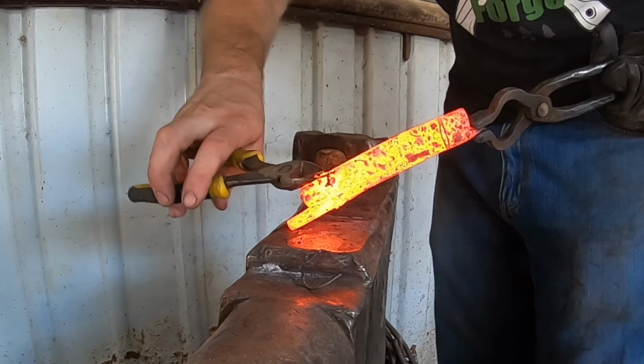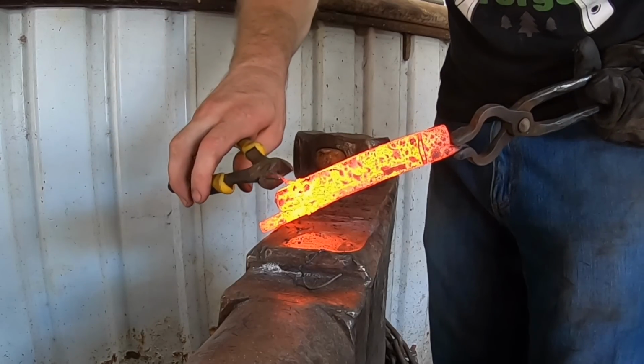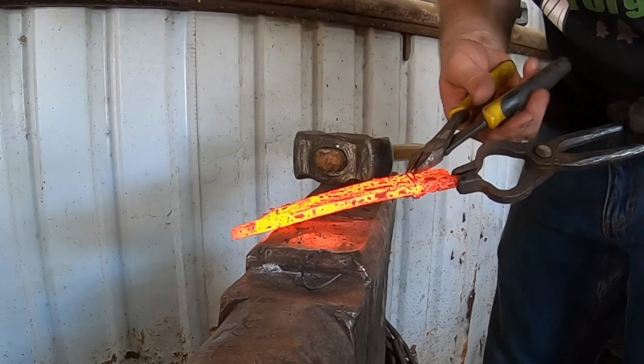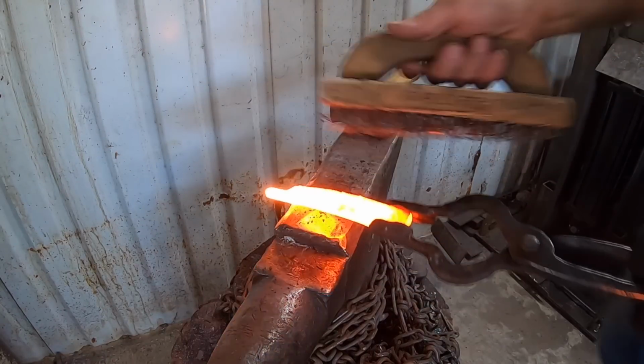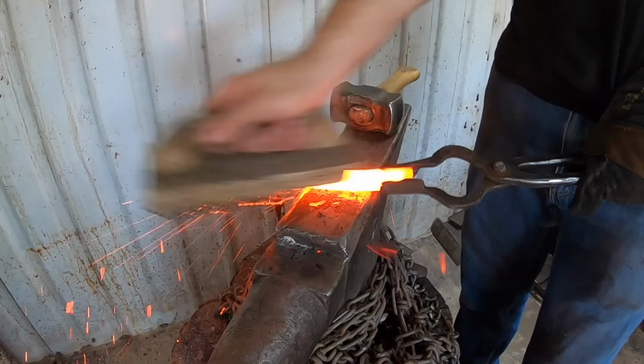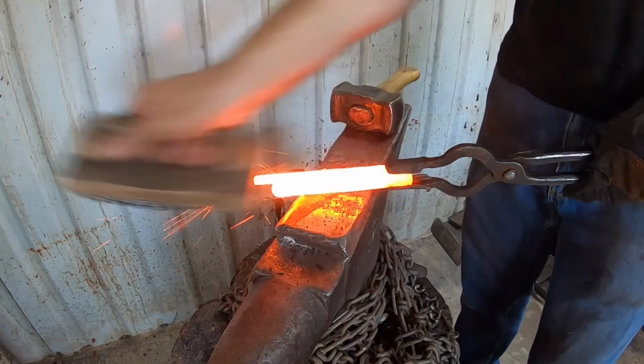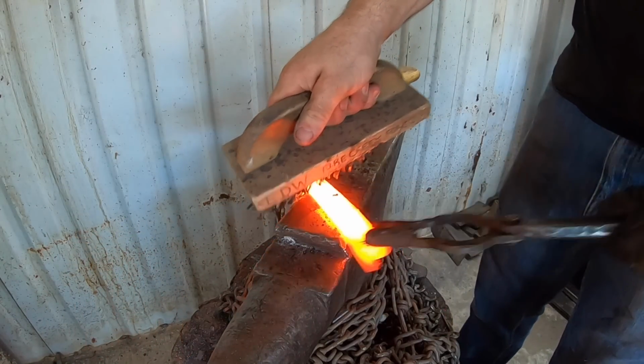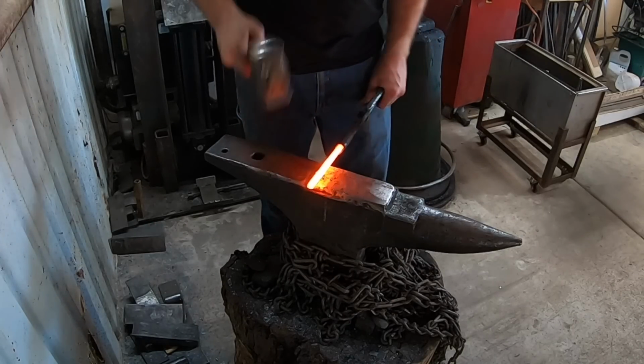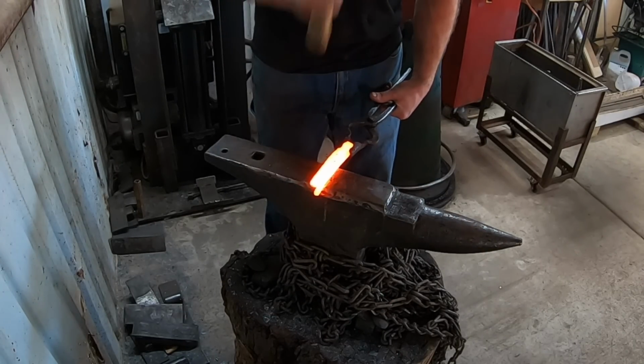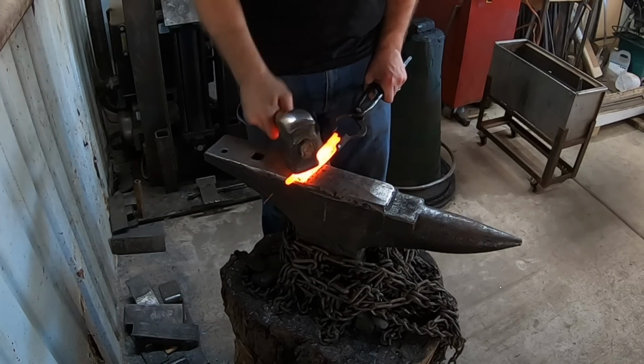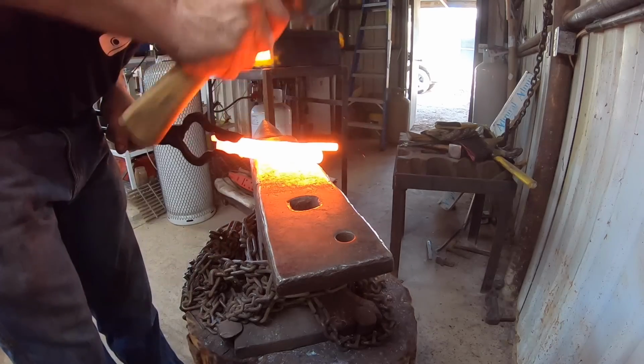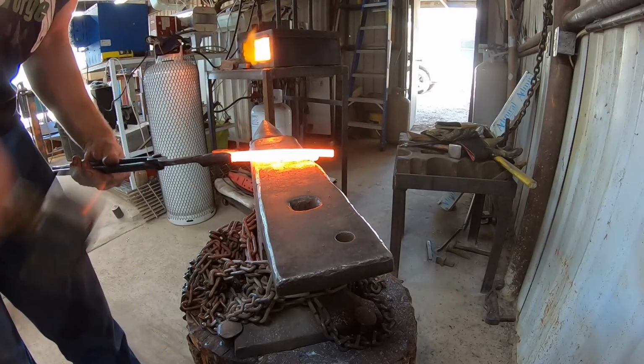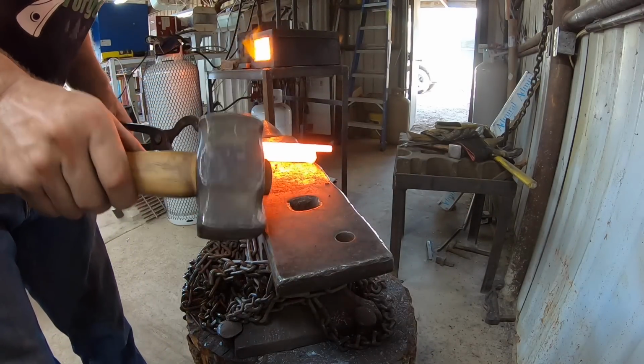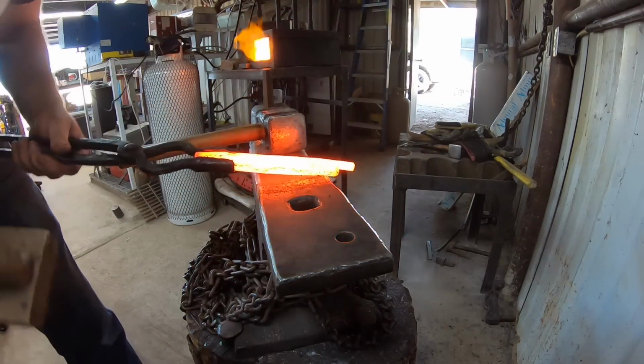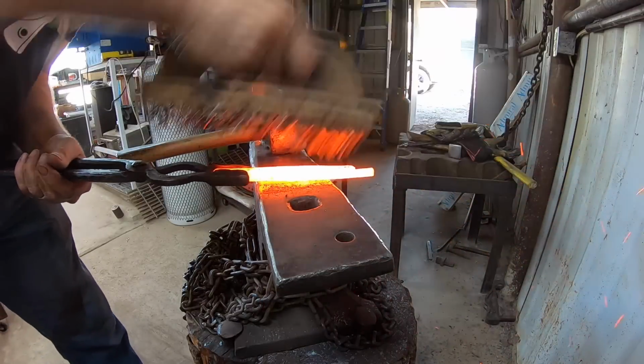So now that we have the billet mostly welded together, I got a little bit on the end here that was separating slightly, but it's stuck together, and I can go ahead and take that wire off, which did partially weld to the outside, and I ground that off as well. So kind of straightening this out a little, flattening this out a little bit. This is where you're going to see if your forge weld did in fact stick, and I had to fix a little bit on the end there and get that stuck back on at a little bit higher heat, and we're good to go there.